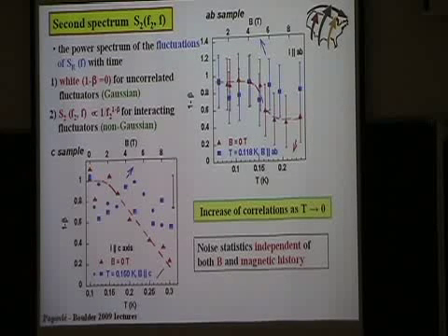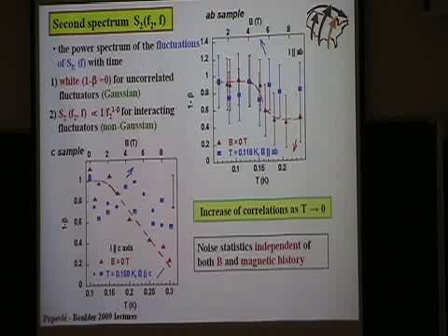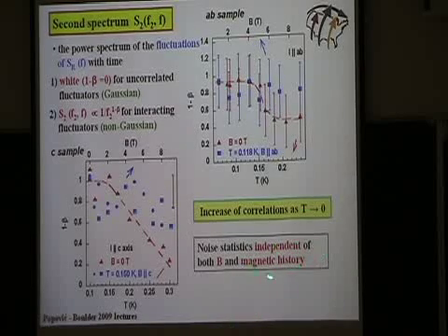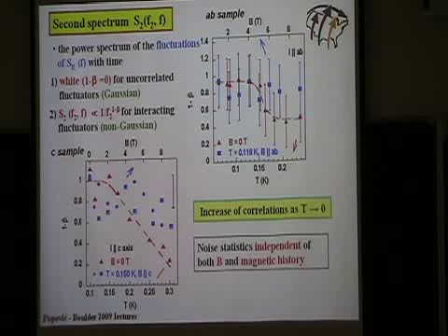We have also done field cool measurements, and in fact in magnetotransport we see a strong difference in the resistance between field cooled and zero field cooled data. However, this history has no effect on the noise statistics.